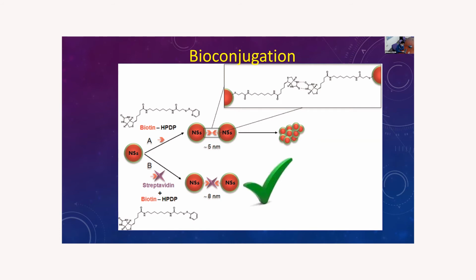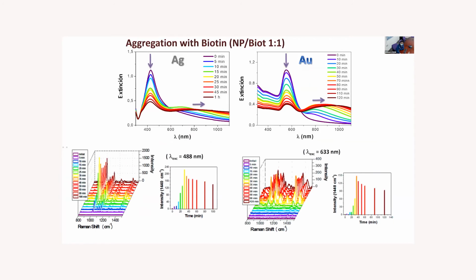In our case, the concentration of molecules will be higher. And what we observe is that, independently of whether we were using silver or gold, the nanoparticles start to aggregate. And at some point, you can see this graph and also this, in the case of silver and gold. We will start to have a very strong Raman signal, in this case SERS signal, but after, in this case, 30 minutes or more or less the same time, the signals start to decrease. Why? It should be something related to this dynamic process. You start with a very stable colloid, and these colloids start to aggregate.